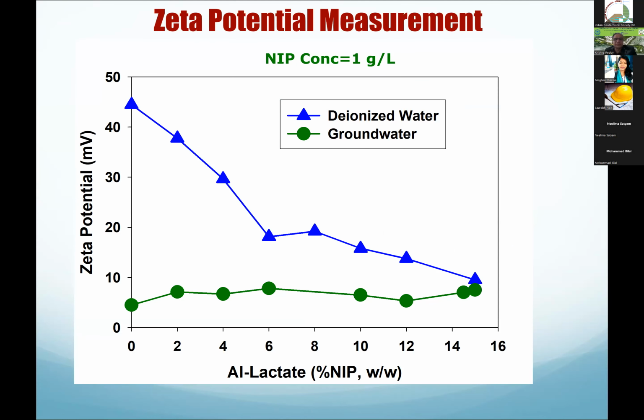This is an interesting result. A lot of times what happens is we do the experiments in our lab using deionized water. We think deionized water is idealistic, we don't have a lot of impurities, and we don't know the effects of those. And groundwater has ionic strength. So what we did is we did the deionized water. So you see, in deionized water, after a certain amount of aluminum lactate the decrease will be less, but you can see the zeta potential decreases, right? Initially it's high and then it decreases.